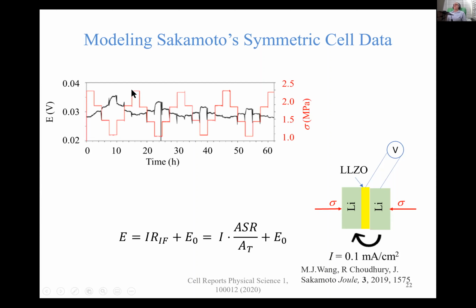So here is his data. The red data is on the right, and it shows how he varies the stack pressure. He starts out at 2 megapascals, and over 10 hours drops it to 1, and then brings it back up to 2, and then he has 4 cycles like this. And then simultaneously, in the black data, he's measuring the voltage drop across here.